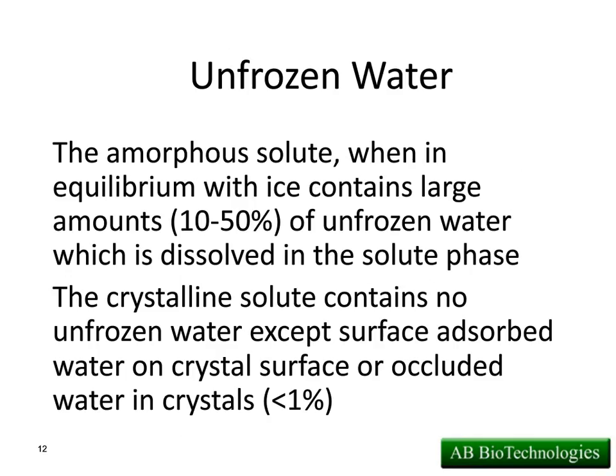Okay, unfrozen water, and this is something that we definitely see in freeze-dried products. Now, you ask, how can we have unfrozen water if we're taking a product down to negative 45? Well, it exists in the interstitial space. So all the ice in the ice channels, yes, it will be frozen, crystalline, solid. However, with the amorphous solid, if we've got a glassy phase, it has water embedded inside it. It acts as what we call a plasticizer, but it's not crystalline water. It's unfrozen water. And we can sometimes trap 10 to 50% of all the water in the formulation inside this amorphous phase.